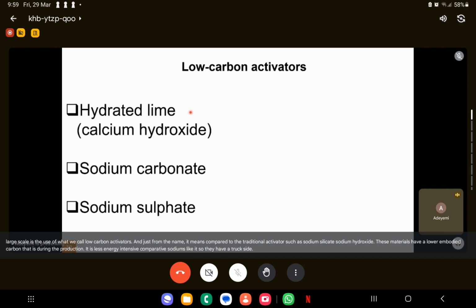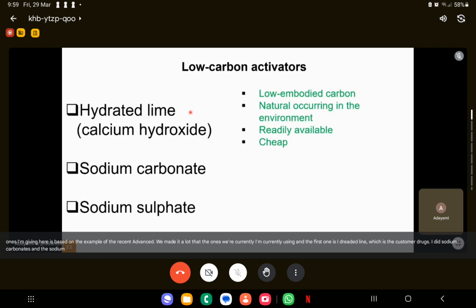And there's about five or six that's available right now, but the ones I'm giving here are based on the recent advances we've made in our lab, the ones we're currently using. The first one is hydrated lime, which is the calcium hydroxide, then sodium carbonate, and sodium sulfate. All these three alternatives, first, they have low embodied carbon. In fact, most of these are found in the environment. So sodium carbonate basically occurs in the environment as a natural source, same thing with sodium sulfate.